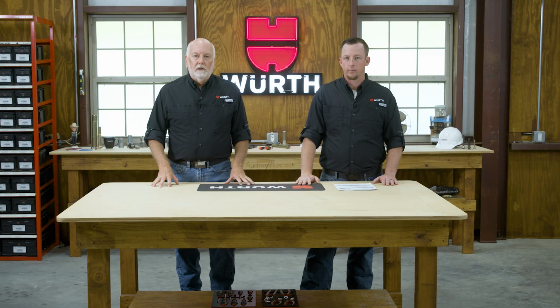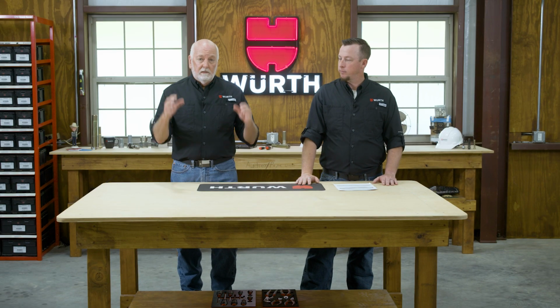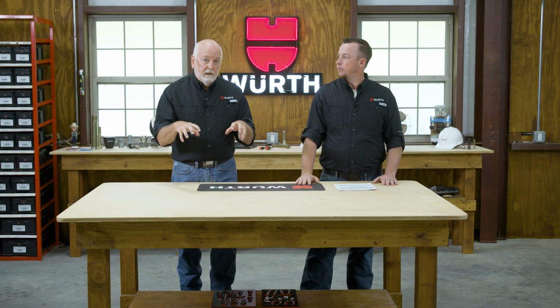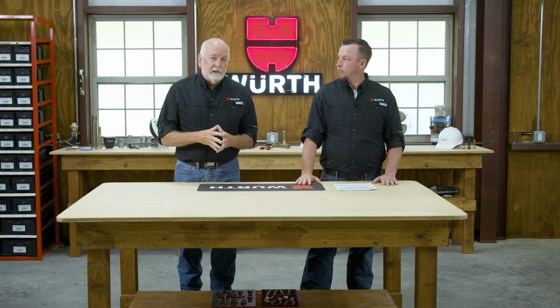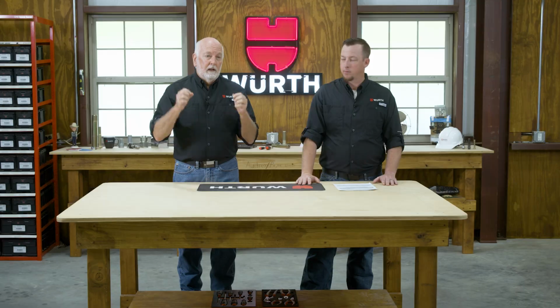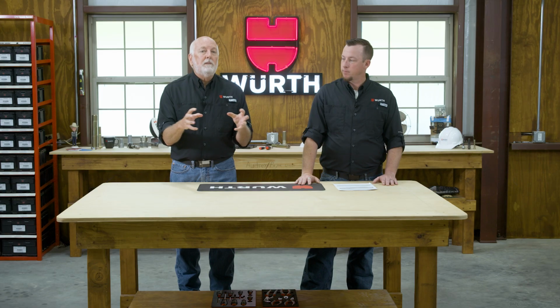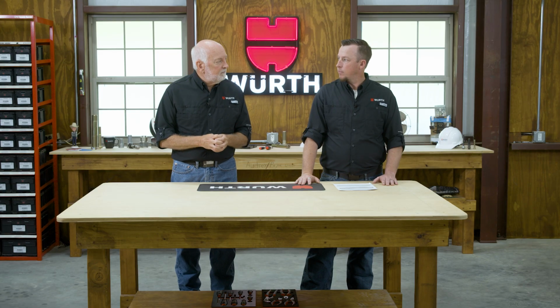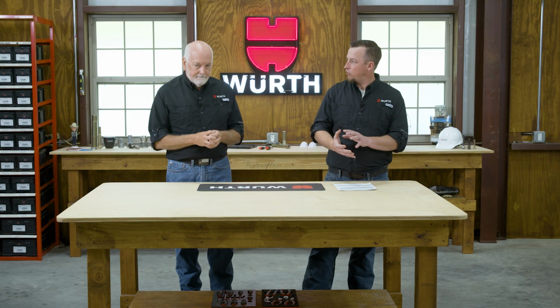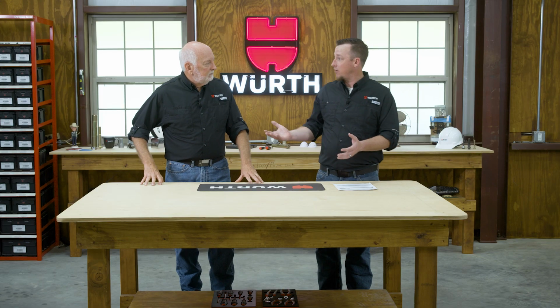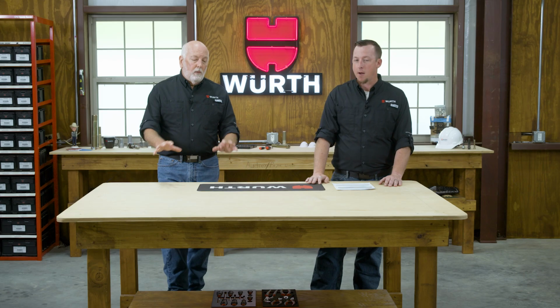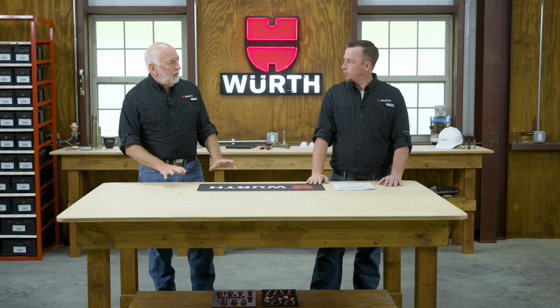So in conclusion, hot dip galvanized, dipped in molten zinc, is excellent for external applications, and then mechanical plating, galvanizing, where we use our glass beads to ping metallic powders onto the metal. Right, creates that nice even coverage. We know that it's not going to cause hydrogen embrittlement concerns, or HE, as we call it a lot in the fastener industry. Correct. A point on the chromate that I do want to make is we found